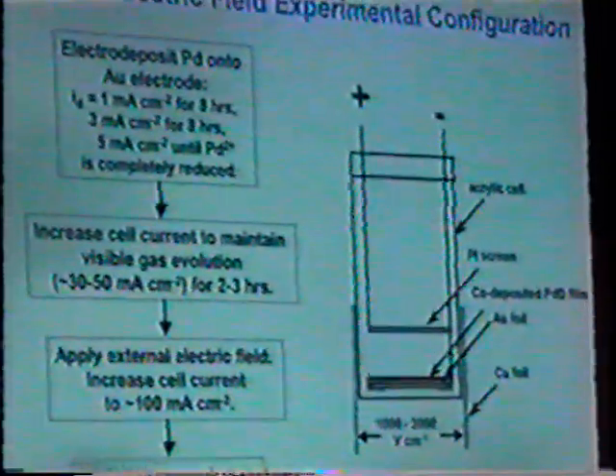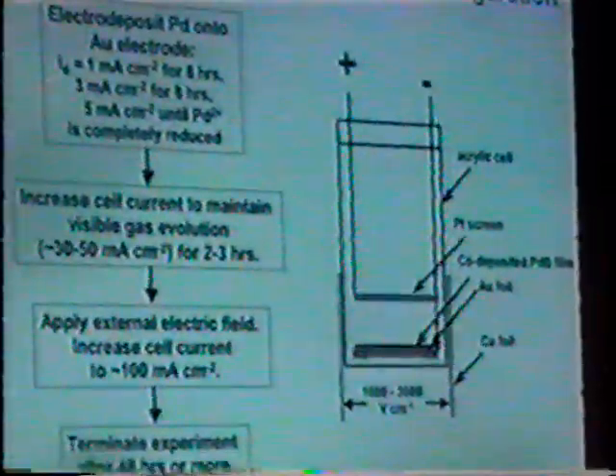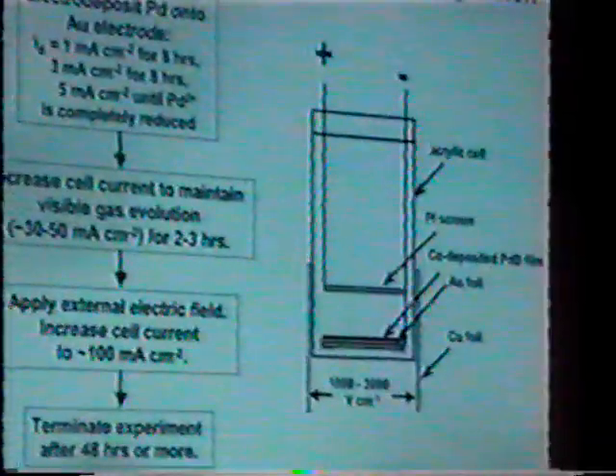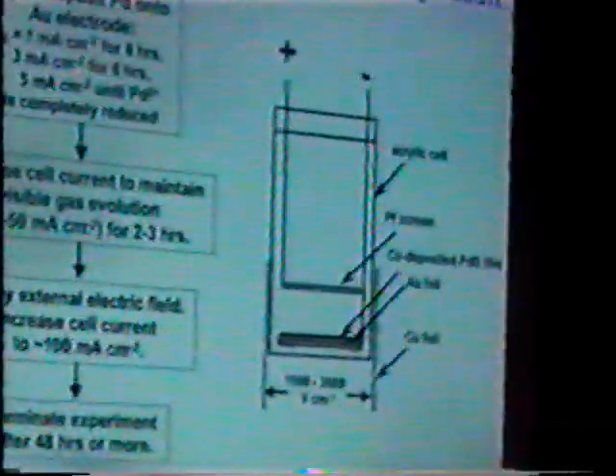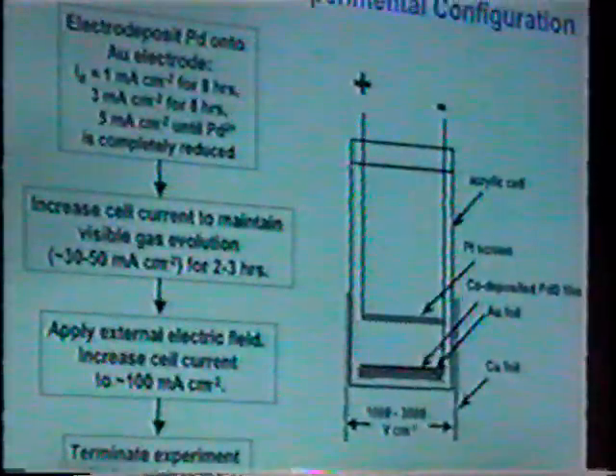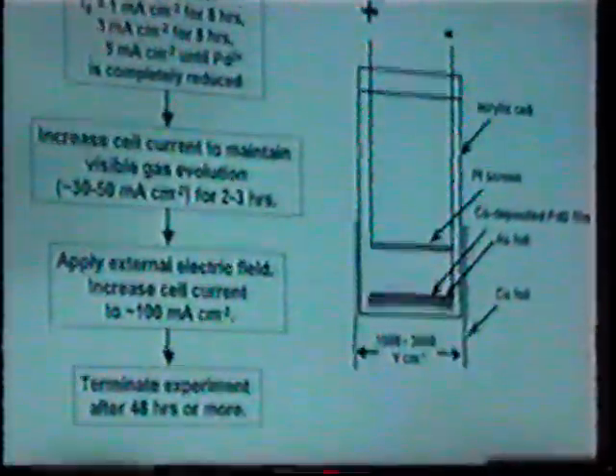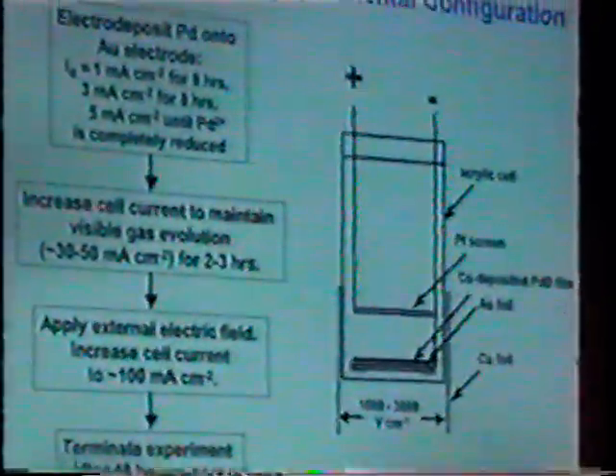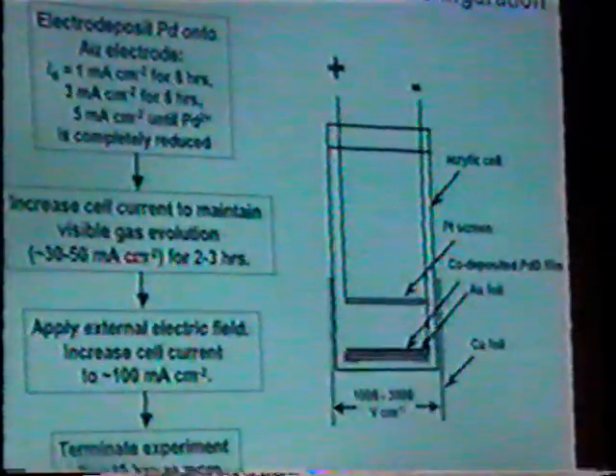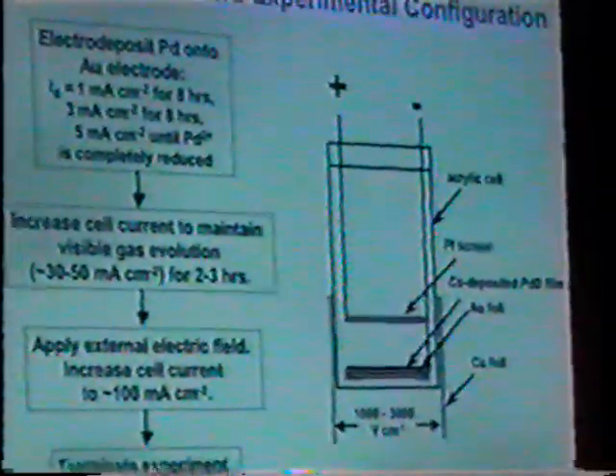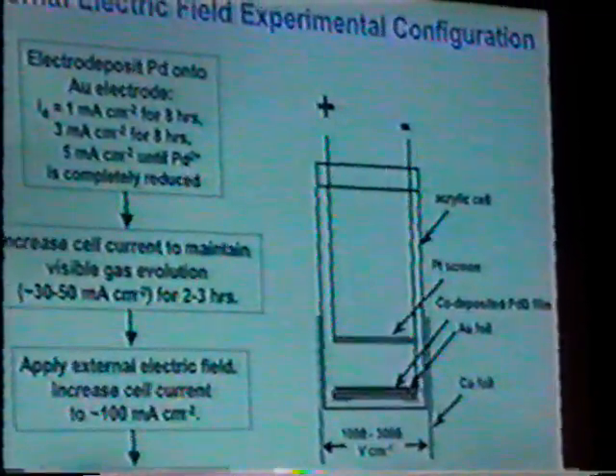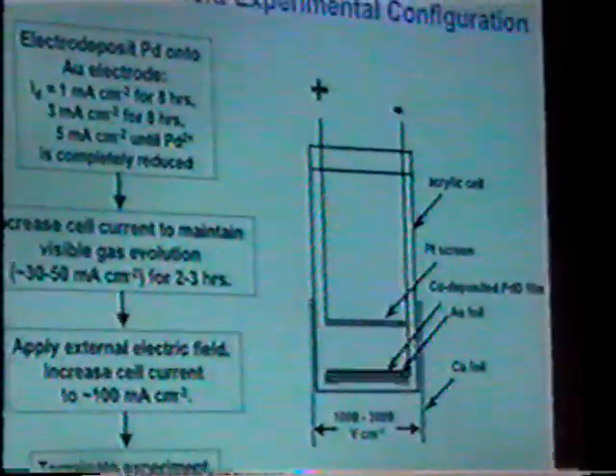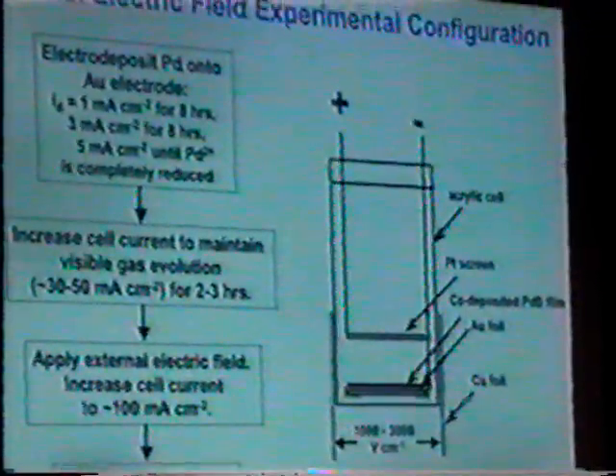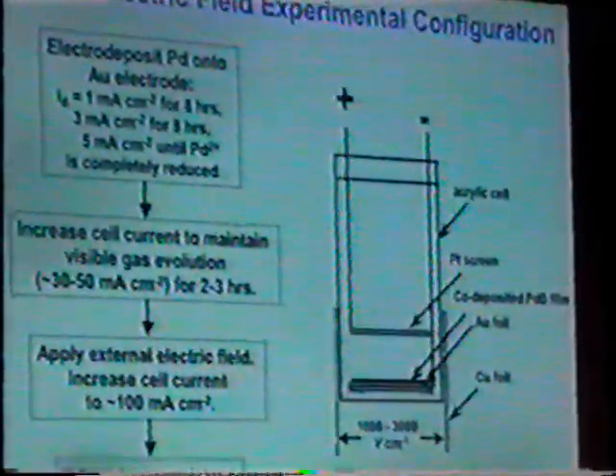Now, the most recent stuff, which is really mind-blowing, involves applying these electric fields. They electrodeposit palladium onto a gold electrode, and here are the currents that they use. It's small, it grows, and then they increase the cell current up to 30 to 50 milliamps for about 2 hours. Then they apply an external electric field, and they increase the cell current to 100 milliamps. They terminate the experiment after 48 hours or more, and this shows the basic geometry.